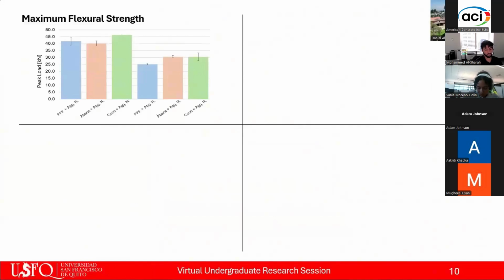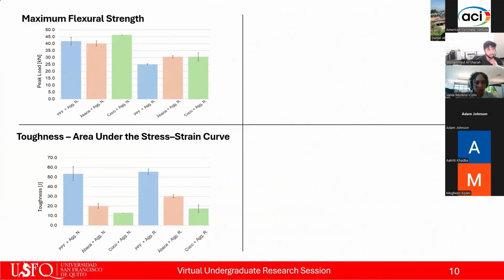In peak flexural load, coconut fibers were the strongest with natural aggregates, carrying a little over 45 kilonewtons, while polypropylene followed at just about 40 and abaca slightly below that. With recycled aggregates, coconut again led at around 30 kilonewtons, very close to abaca, while polypropylene dropped noticeably to about 25 kilonewtons. For toughness, recycled aggregates had a clear benefit. With synthetic fibers, energy absorption reached around 55 joules, well above the values of the same mix with normal aggregates. Overall, the fiber type defined the response. Synthetic fibers delivered the greatest toughness, while coconut fibers allowed lower energy absorption.